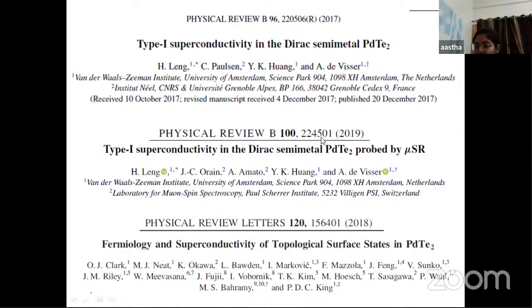However, this type 1 superconducting phase in PdTe2, a binary compound, came as a surprise, because these binary compounds are generally expected to show type 2 superconductivity. So later, a type 2 superconducting phase was also observed by Clark et al., where they observed a vortex core at an applied magnetic field of 7 millitesla. Based on this observation, they claimed that the superconducting phase in PdTe2 is of type 2 nature.